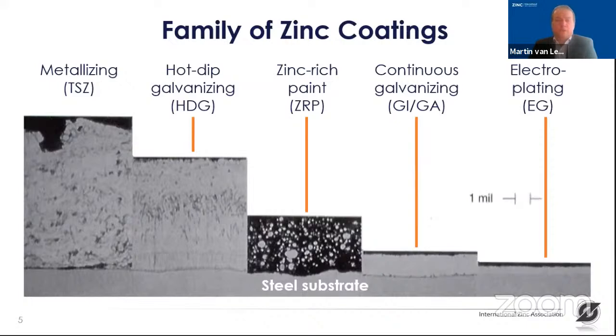The thickness of the coating is flexible by the amount of passes you will have with the spraying gun on the substrate. The second category is hot-dip galvanizing. There, the coating thickness is a little bit dependent on the type of steel that you galvanize and the thickness of the steel that you galvanize, but you will find typically coating thicknesses between 60 and 100 micrometers.